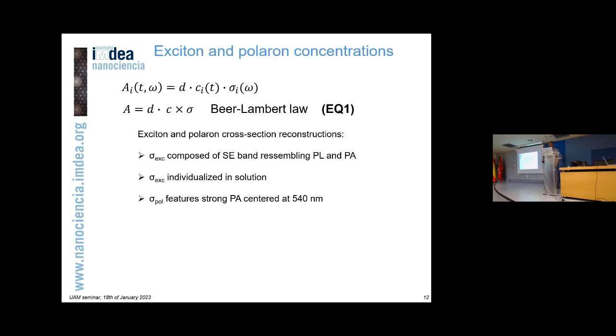When you perform these experiments in solution, essentially you are isolating what we call intrachain species, which are located on a single chain. When you aggregate the system and look into the properties of the film, you observe additionally contribution from species which are stabilized between different chains, such as polaron pairs. So by performing both experiments, we can disentangle one contribution from the other.